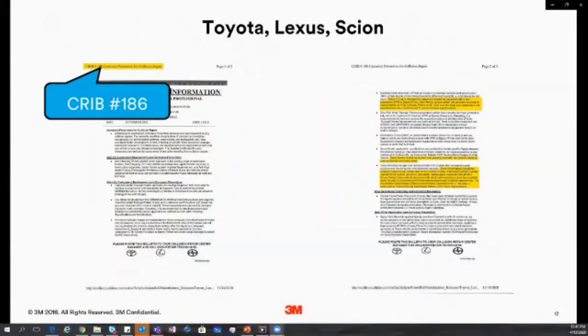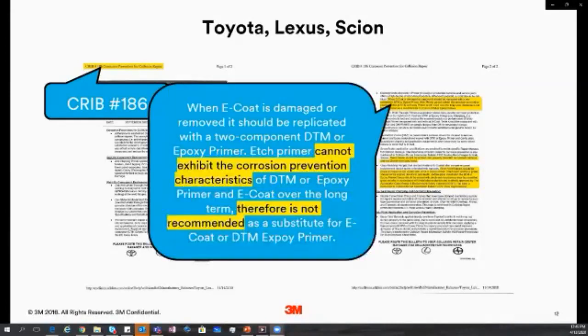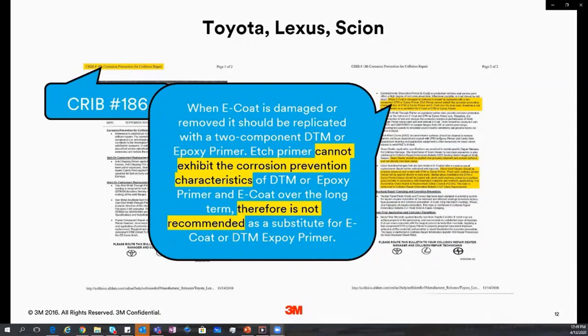It's Crib 186. And I really like using this one because they really paint a picture that is without doubt unquestionable on their statement, right? They're very clear about what it is that they want. And one of the first things that they talk about in their statement is the fact that when the E-coat is damaged, it needs to be replicated with a two-component direct-to-metal or epoxy primer. And they're very specific in saying an etch primer cannot exhibit the corrosion prevention characteristics of a direct-to-metal or epoxy primer and E-coat over the long term. Therefore, it is not recommended, right? So it's not recommended as a substitute for E-coat or a direct-to-metal epoxy primer.